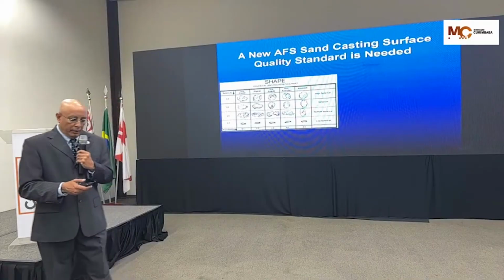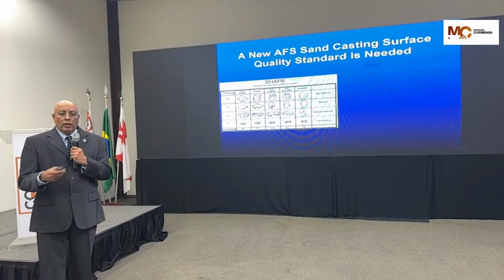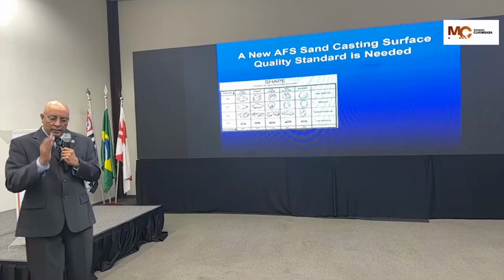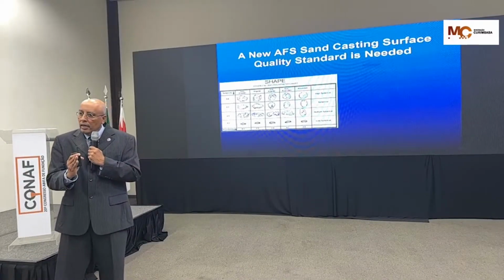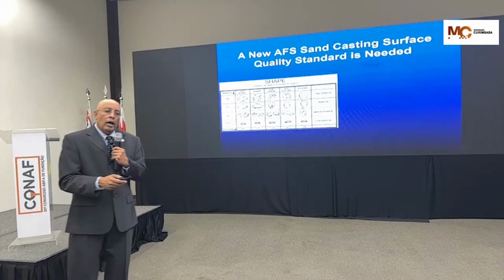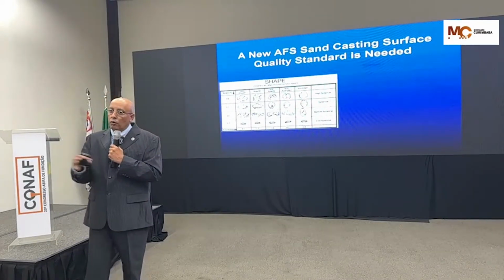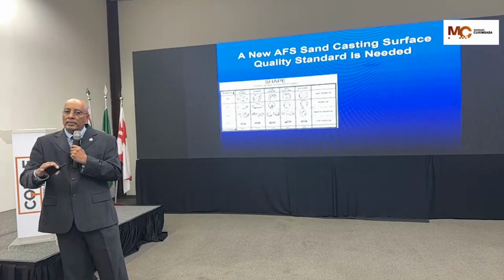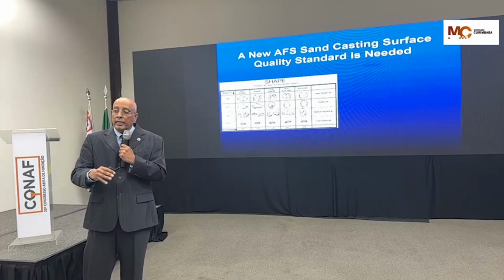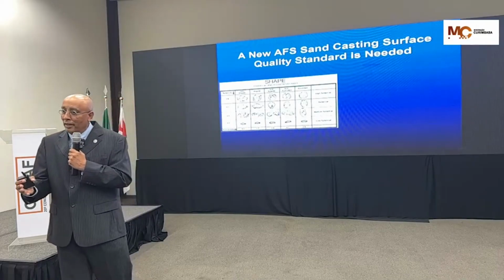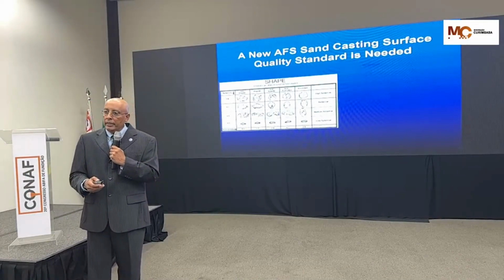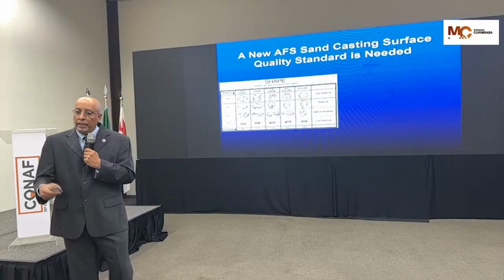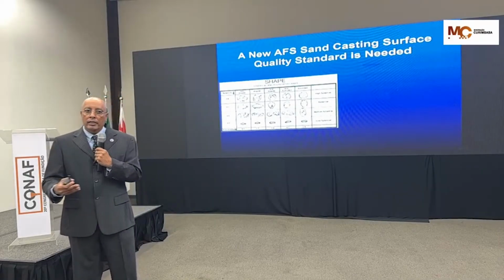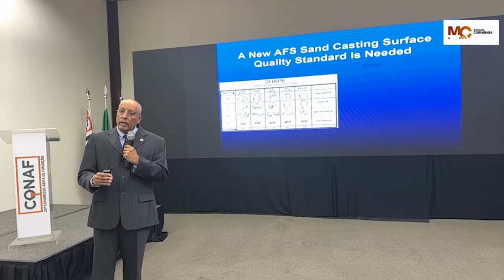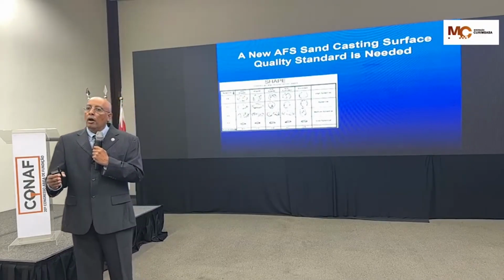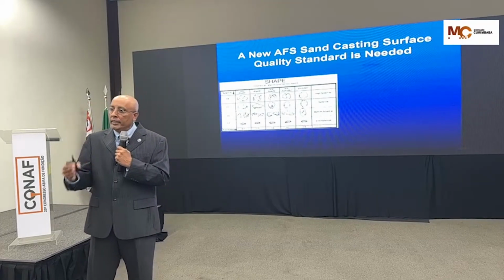Why I'm saying this is because when we measure the grain fineness at AFS, that just gives us the average particle size. And the number of screens is a distribution in foundry work that continuously changes as the sand is depreciated and predominantly gets finer. But when that sand gets finer and finer, it ultimately increases the surface area. And surface area, in my opinion, is a major factor driving strength. But strength is only one property of a granular material that we need in metal casting.